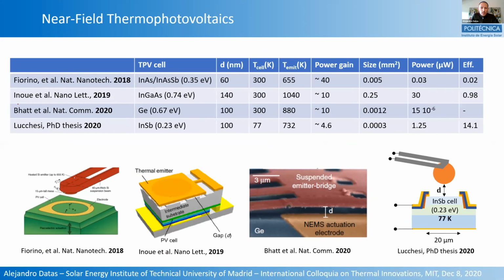Well, just to make a brief overview of the state of the art, I'm writing here the 4 main experimental results proving this concept. This is the one that I showed before, but there have been 3 others. And remarkably, I want to emphasize the date of the publication. So these are really, really recent results. So you have different cell materials with different bandgap energies, from extremely low bandgaps of 0.2 or 0.3 electron volts to perhaps more convenient bandgaps of 0.74, 0.67 for germanium.